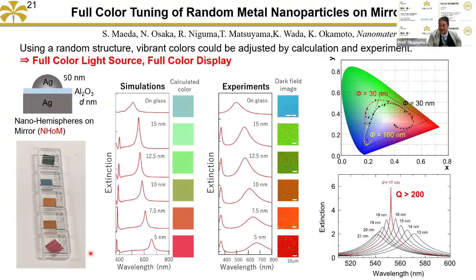Yeah, that's a very, very important point. The peak splitting depends on this distance. As the distance gets closer, the separation becomes wider and wider. But the sharpness and the intensity are a balance of both electric fields. If so, it's more of a dark mode, the quality factor is larger and it becomes sharp, but the balance is not so good, so it becomes a bright mode. That's why this very sharp region is a very good balance between the metal nanoparticle electron mode and also the substrate mirror image mode. Yeah, I think so. Thank you very much.